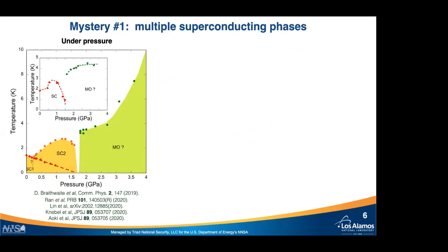So this is a temperature pressure phase diagram of this material. It's interesting that the TC, the superconducting transition temperature, decreases at first, and then it seems to increase and actually split into two. One of them increases, the other one decreases, and then at some pressure around 1.5 GPa, there is an abrupt change from the superconducting state to something that looks like a magnetically ordered state.